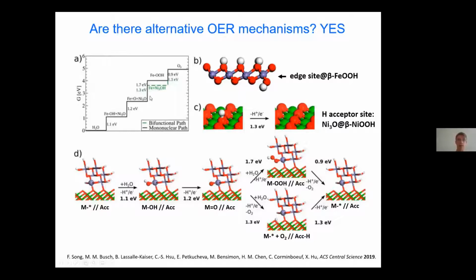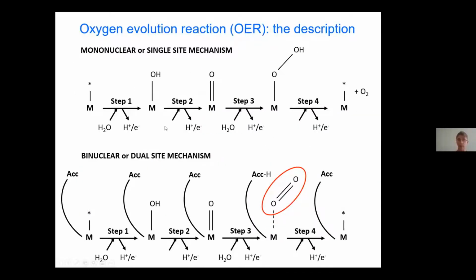So here you see that the reaction can happen with the acceptor site at an overpotential that is 0.4 volt lower than with a pure iron OOH system. So that's computationally calculated. So again, to repeat what happens, we compare the mononuclear or single site mechanism with the binuclear or dual site mechanism. So within the dual site mechanism, we have this empty metal site, we go through a metal OH, then metal oxo, and then in the third step things happen that are crucial: water attacks, we eject the proton electron pair, we generate oxygen, and we hydrogenate the acceptor site.